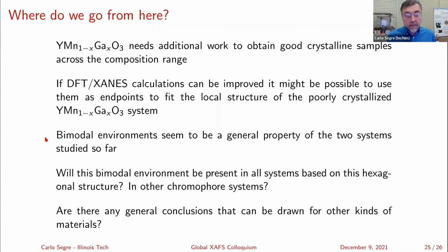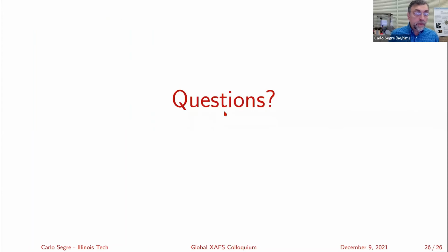I don't have these slides today, but we've seen this kind of behavior in other systems, as I mentioned before. We know that these local structural effects dissipate spatially, and so you can see by diffraction that things look uniform, and clearly these global properties, these bulk properties, actually can come from this disproportion. It's not really disproportionation, but this local phase separation or nanoscale phase separation, which I find very interesting. It happened to be the case for the lanthanum barium cuprate in the high TC materials. So if there are any further questions, that's pretty much all I had for today.